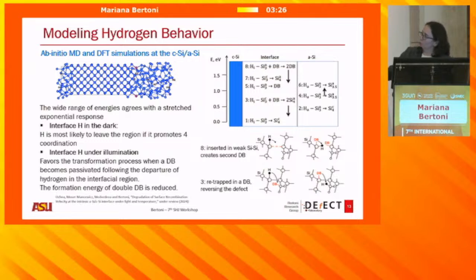The first one really is a hydrogen bonded to a silicon 3 in an amorphous state that would always tend to crystallize. And this makes sense, right? You are very familiar with trying to apply some heat to amorphous silicon and how it tends to crystallize, right? So the next thing that we asked them was, okay, what happens if you shine light?